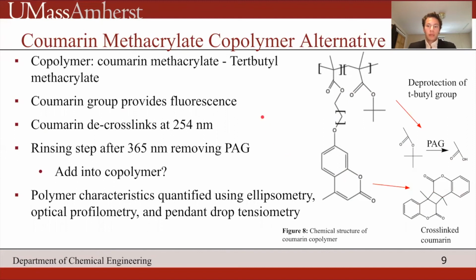However, the 254 nanometers used to activate the PAG decross-links the coumarin, and so another step needs to be added of recross-linking at 365 nanometers to recross-link the coumarin. The rinsing step after the first cross-linking step has been shown, however, to remove some PAG, and so what we're currently working on at this point in my thesis is the potential of adding PAG directly into the copolymer as a third methacrylate group, a methacrylate PAG monomer, which would therefore make it so that the PAG is completely dispersed within the polymer, and fully deprotects when irradiated at 254 nanometers. Another option would be to spin coat the PAG on top of the uncross-linked polymer or to increase the concentration of PAG mixed in.